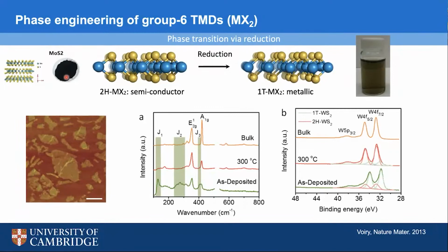It involves taking the powder of these layered TMD compounds. In the case of MoS2, the 2H phase, the trigonal prismatic phase, is a thermodynamically stable phase. We simply put this MoS2 powder in a solution of butyl lithium. And so we have charge transfer from the butyl component of the butyl lithium, which is then stabilized by the counter lithium ion.